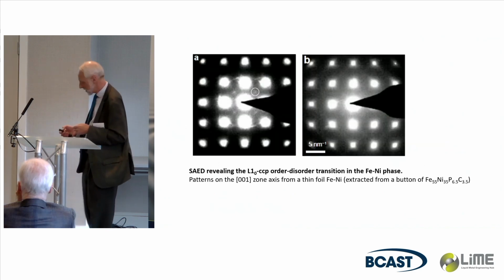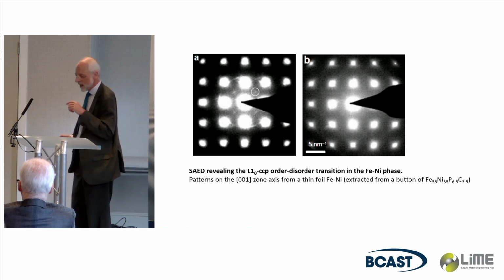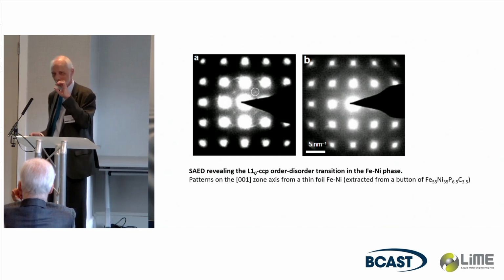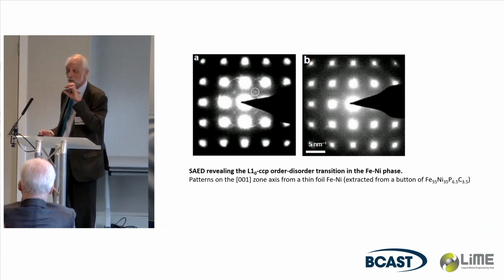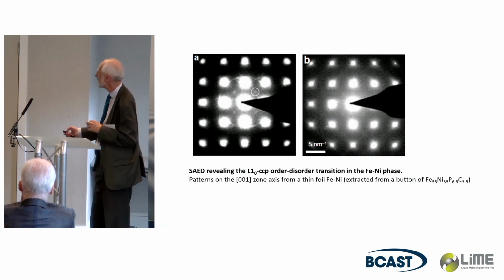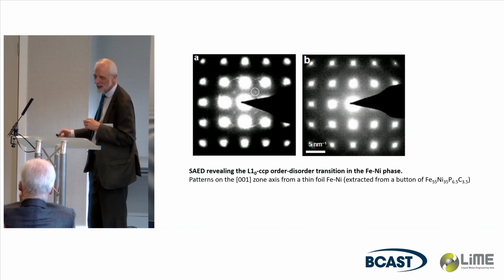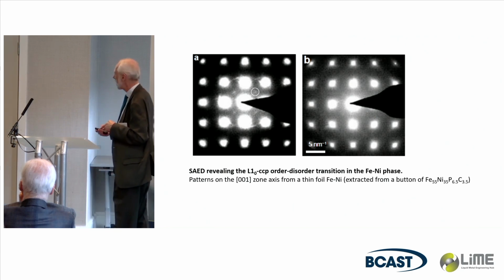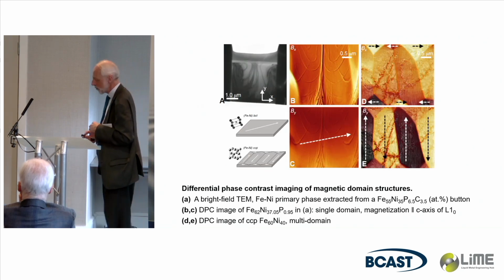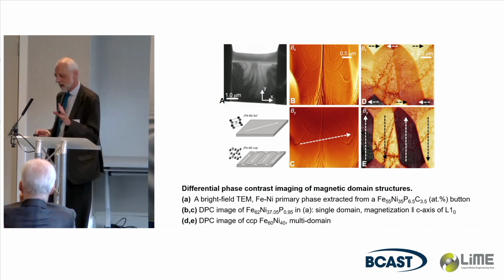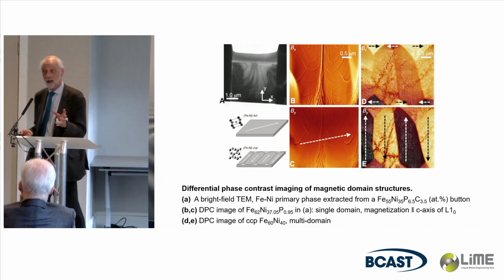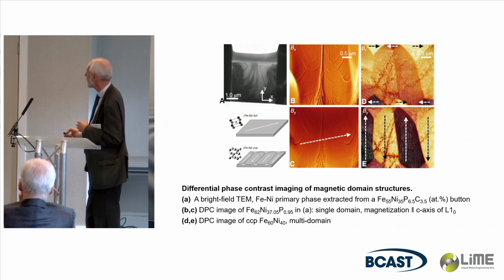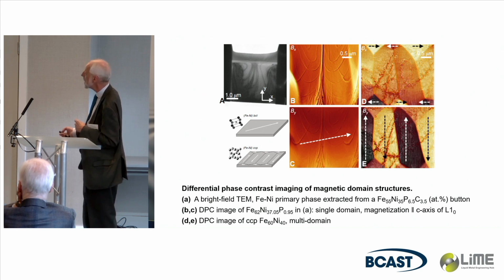The critical evidence in my mind was this, that, of course, once you make it slightly tetragonal, some of the things that are forbidden reflections for FCC are no longer forbidden, and here they are, they're showing up. So that was our little story. We could not possibly claim to have characterized the magnetic properties in any serious way, but the preliminary study in the microscope shows that the tetrataenite sample shows large single domain regions. This is 1 micron scale bar here, half a micron here.